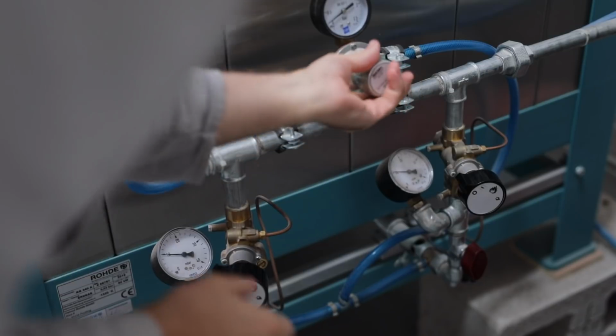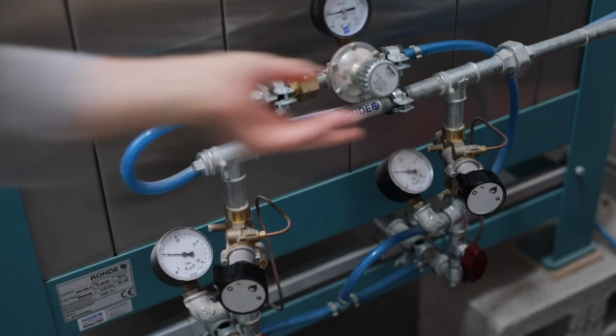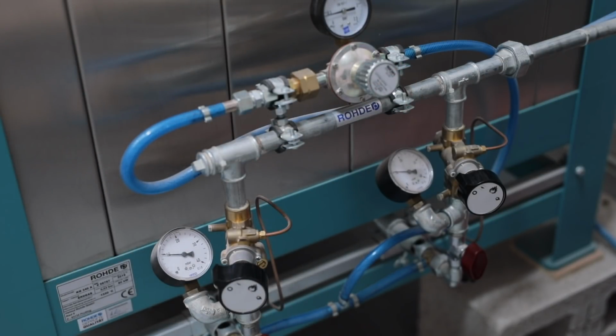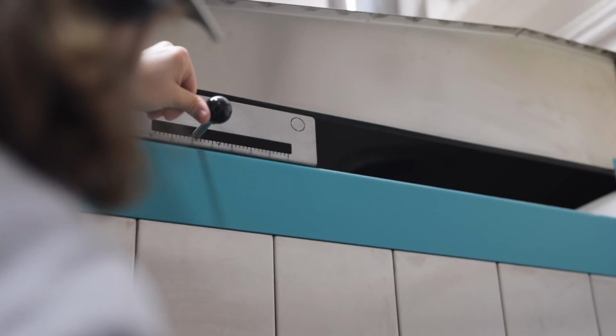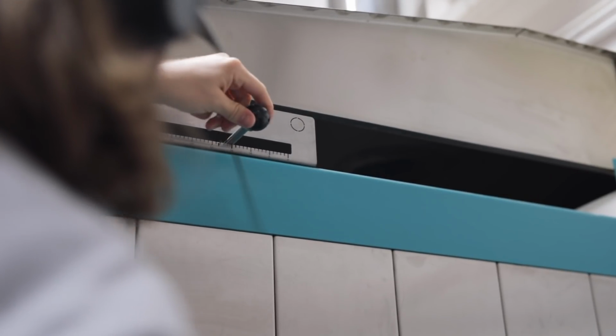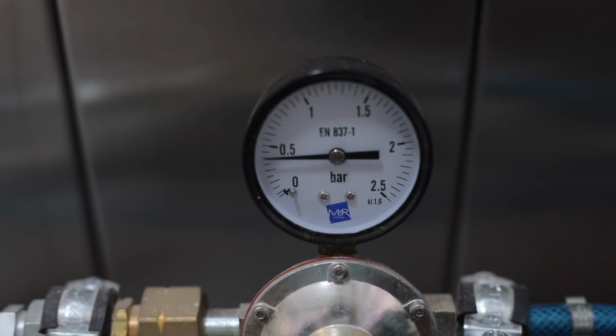I do this by increasing the gas pressure to 10 mbar and the compressed air to 0.4 bar. And perhaps most importantly, I slide the damper so it's about halfway closed. This causes the gas inside to burn inefficiently, as the exhaust can't exit the throttled kiln quickly enough, which means that there simply isn't enough air inside for the fuel, in this case natural gas, to burn properly,